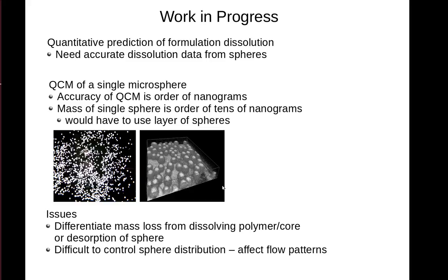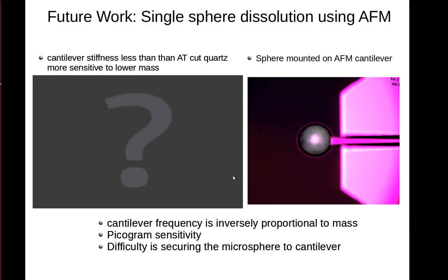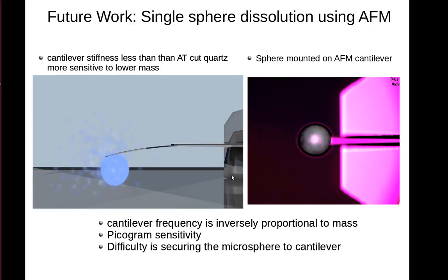What we really need is an oscillator with a lower stiffness and therefore the sensitivity needed for the single sphere. Fortunately, it turns out that we already have that in-house. The cantilevers used in atomic force microscopy have approximately the right stiffness to be able to measure the mass change of a single microsphere. On the left, we see it's based on the same principle. As the mass of the microsphere decreases, the oscillation frequency of the cantilever increases.